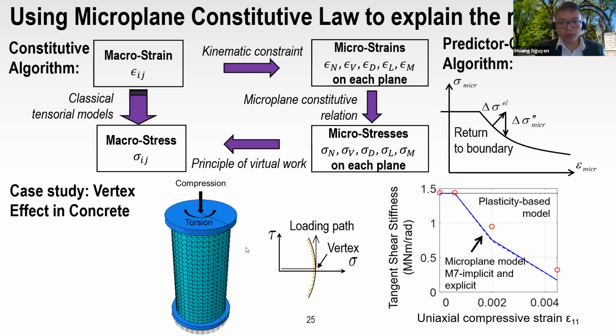And the important, cool case about the microplane model is that it can simulate the vertex effect. The vertex effect is a loading path where you first compress the cylinder and then apply torsion to it. A plasticity-based model will predict constant stiffness for this loading scenario. However, in experiments, they show a decrease.